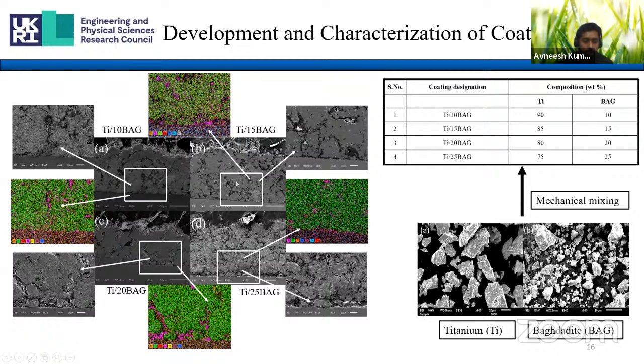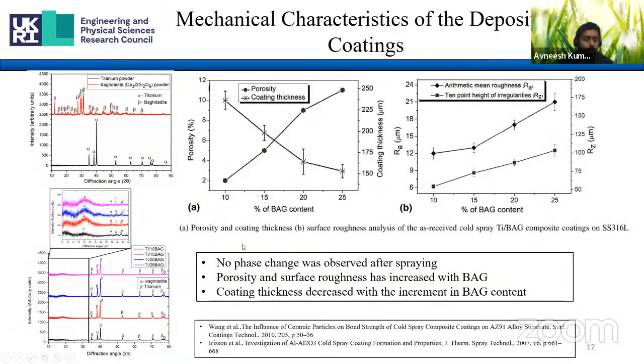These are the etched cross-section images of the coating. From here, we can see that a significant amount of ceramic has been retained in the coating. To confirm the retention of the particle in the coating, we took some high resolution SEM images at different locations and mapped them. Then we used image analysis software to see how much percentage of Baghdadite is retained. We found that around 60 to 85% retention was there, and that also depends on the coating composition. The main thing was the phase change problem, which we were having in plasma spray coatings. Here we did some XRD analysis, and we have seen that there was no phase change in the coating after the spraying.